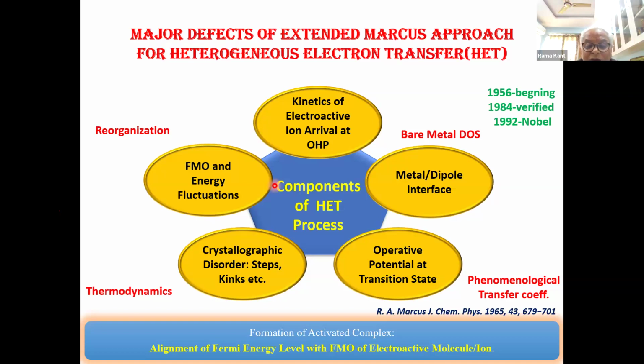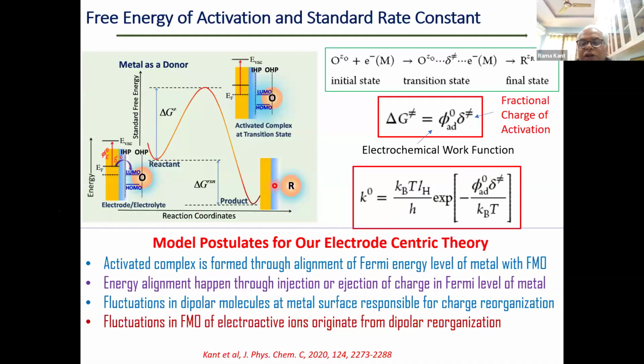So basically in our theory, we say alignment of the Fermi energy level with the FMO of the electroactive molecule or ion is responsible for electron transfer. So our activation energy formulation has two components. One is the electrochemical work function, which is directly measurable in electrochemistry as the potential of zero charge. And there is a fractional charge of activation, because the FMO and my metal, their energy levels are separated. To make them transfer electrons, they have to become equal. So this delta dagger represents the fraction of charge required either to inject or eject out of my, say, metal Fermi level to make them equal. So these are the two components. The whole thing is how to model these two things microscopically so that we can have all microscopic components: electrolyte, supporting electrolyte, the size of ions, type of metal, any solvent, formation of adsorption over the interface. All those complexities have to be accounted for.